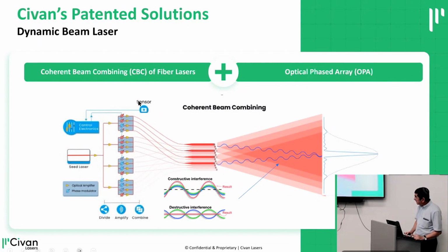The way it works is we have here many lasers. Our basic product has 32 lasers, and in the bigger ones we use 100 lasers. From every laser, you have optical fiber going to some collimating lens. The light from each of these lasers goes out through some optics and creates a spot. This spot is a few hundred microns, let's say in our case, 300 micron spot, okay? So when you have 32 lasers, each one with 1 kilowatt, and they all, as you can see here, are parallel to one another, each one of them creates a spot of 300 micron with a kilowatt of power. Altogether, they create 32 kilowatts, but with a spot size of 300 microns.